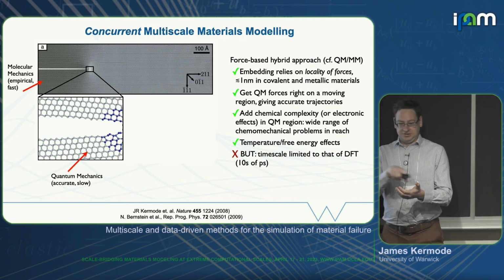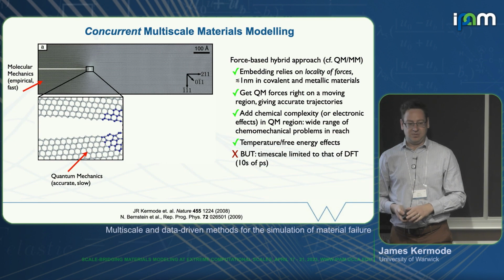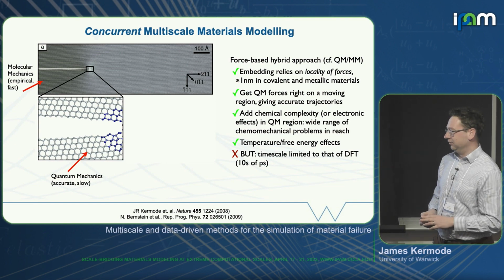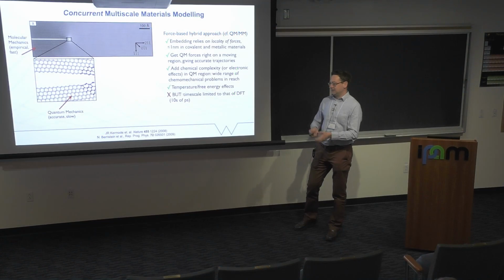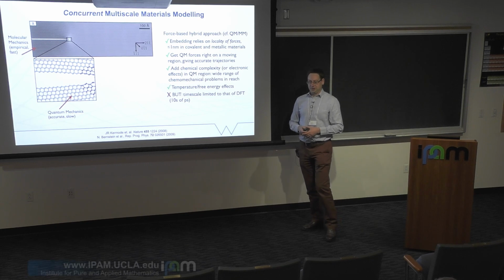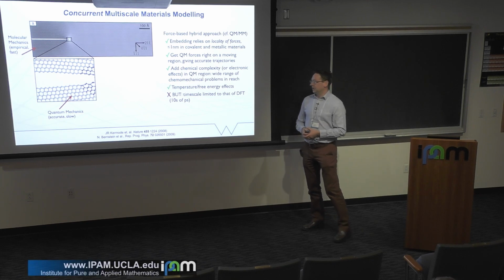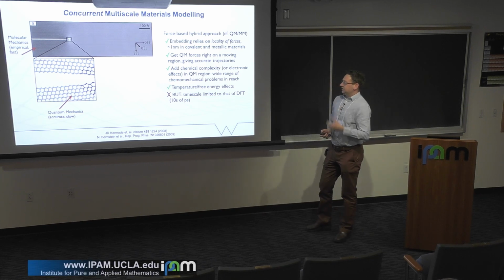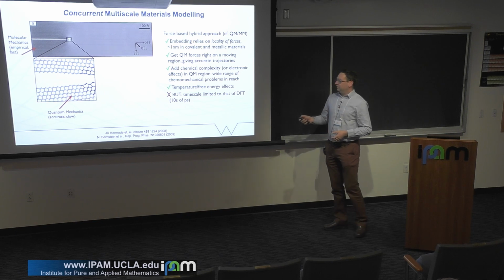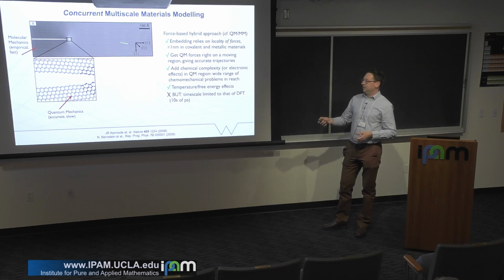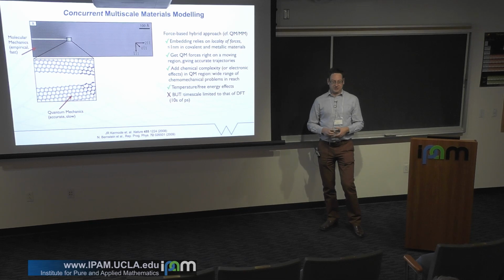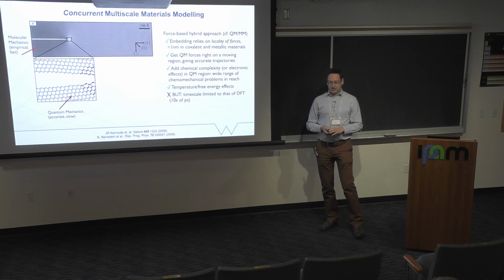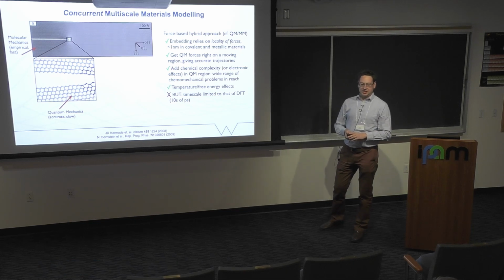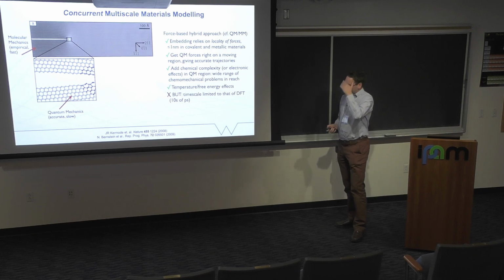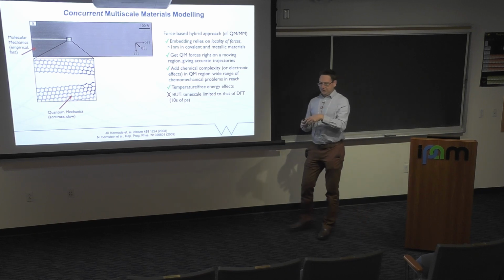And that's because electrons are delocalizing along the surface, they're pi bonding, and so we're getting a different response, and that does affect the fracture properties that will be relevant at larger scales. So the way that this approach works, essentially, is that we compute forces on a quantum mechanical region, we combine them with forces of sufficient accuracy elsewhere in the system, and get an overall set of forces that we can use to advance trajectories.